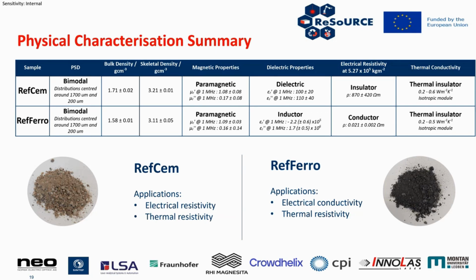So just to summarize there, we have had a look at the characterization of these two materials. We see that they're both bimodal particle size distributions, and their interesting properties really are in the dielectric and electric properties. And we see that we can potentially use the RefCem material for electrically resistive applications, whilst the RefFerro material we can potentially use for electrical conductive applications. Both these materials are also thermal insulators, as we would expect, and so they can potentially be used for thermal resistivity applications as well.